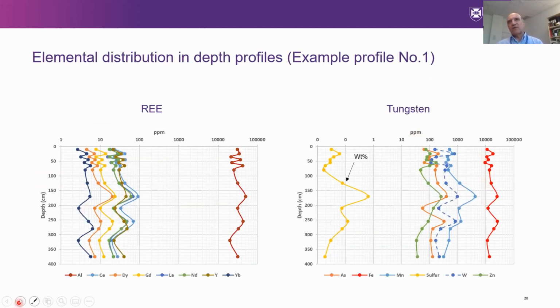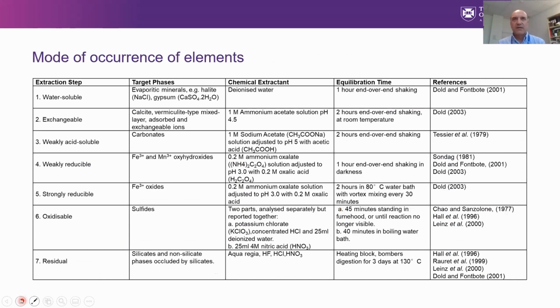So we need to understand the mobility of tungsten. The first thing is to look at the profile samples and see the co-placement and co-location of tungsten with a number of other elements. In this case, for example, on this profile, when you look at zinc, because zinc is very mobile, you can see it doesn't really follow a predictive pattern. Whereas when you look at iron and tungsten, there is some correlation, but whether this correlation relates to just being placed at the same time and having high concentration, or there is a chemical process, this is where we need to do sequential extraction and try to understand the mode of occurrence of that element of interest.